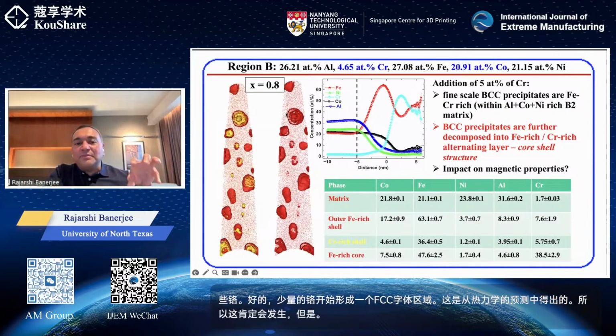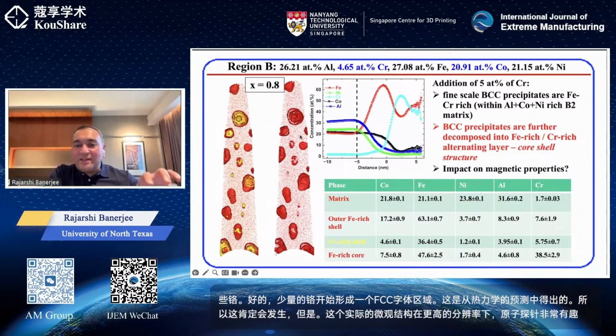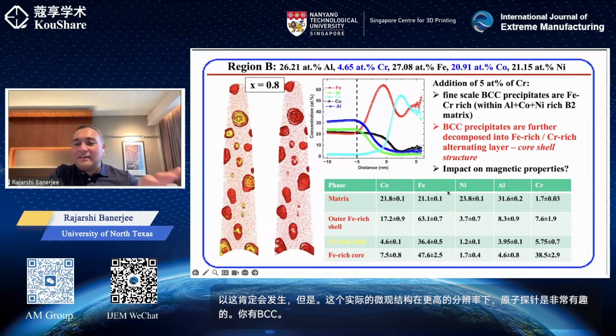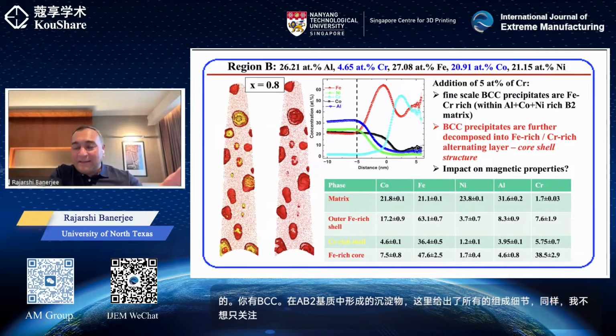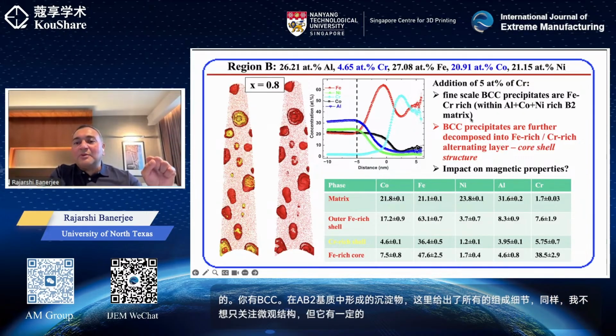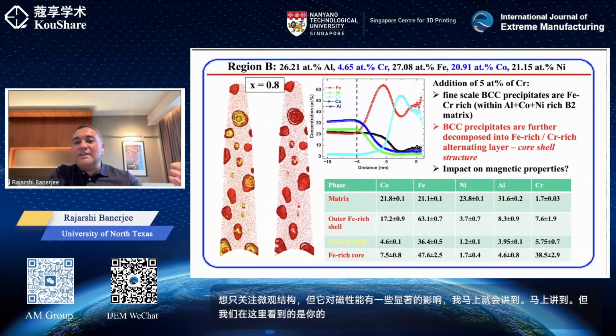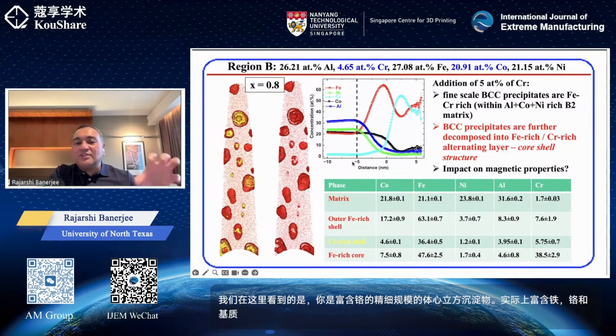You have BCC precipitates that are forming within a B2 matrix. All the compositional details are given here. Again, I'm not trying to just focus on the microstructure, but this has some significant impact on the magnetic properties, which I'll get to in a minute. What we are seeing here is fine-scale BCC precipitates that are rich in iron and chromium, in a matrix of nickel, aluminum, cobalt, which is the ordered B2 phase. So it's a two-phase mixture.